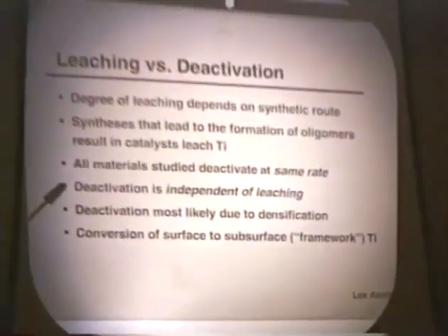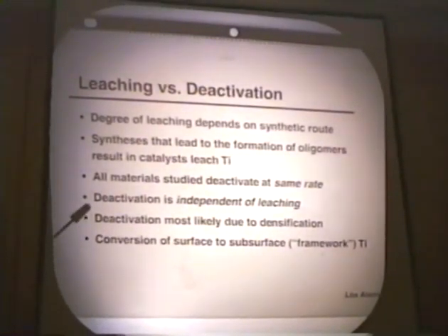The main point that I want to make is that deactivation is independent of leaching. Deactivation is most likely due to densification of this material. I think this probably has implications for the use of MCM in general: these very high surface area materials with high silanol densities seem to have a propensity to densify, and that may have implications for any case where you have polar organic molecules around that are responsible for this densification.